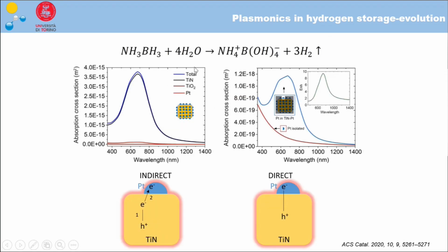Here you can see the absorption of the light in these composite nanomaterials. You can see that most of the absorption is within the titanium nitride structure, and a small percentage of the absorption is within the platinum nanoparticles. But there are also interesting features which happen when you couple, for example, a non-plasmonic material like platinum to a plasmonic material like titanium nitride. You can see from the spectra on the right hand side of the slide, the absorption of the platinum can be resonantly enhanced by the plasmons, if you compare this with the absorption of isolated platinum nanoparticles.